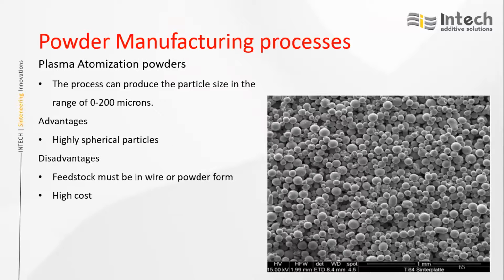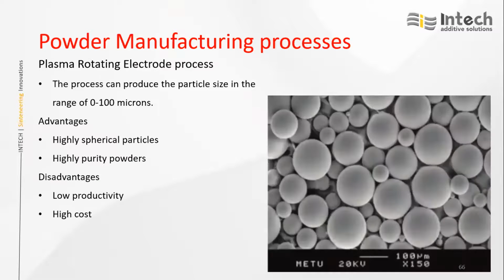With plasma atomization, the sphericity and quality of the powder is still improved compared to gas atomization, but the cost goes higher. With the plasma rotating electrode process, the powders look even better, with more sphericity and very good flowability. High purity powders, but low productivity. With gas or water atomization, the throughput is very high, but here it's very low, so the cost per kg goes high.